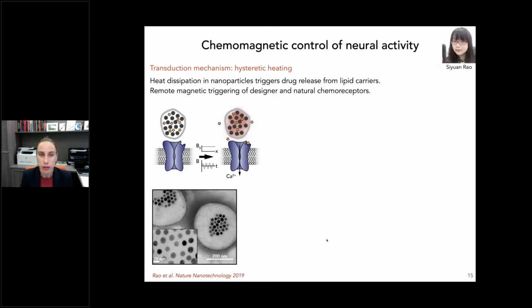But we don't need to limit ourselves to direct stimulation of thermal receptors. We can extend this hysteretic heating to controlling other molecular processes. For instance, we can control phase transitions in lipid carriers. For that, we can design a liposome that is stable in physiological temperatures such as 37 degrees Celsius, but undergoes liquid crystal transition and becomes porous at 42. And that allows us to release water-soluble payloads from those liposomes.